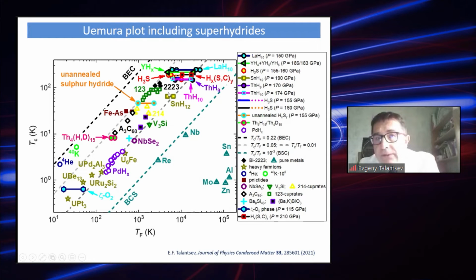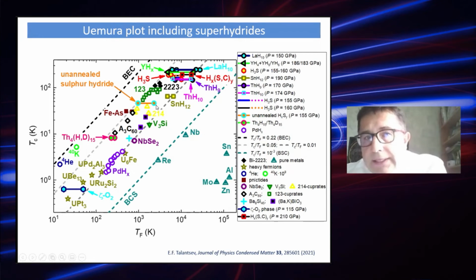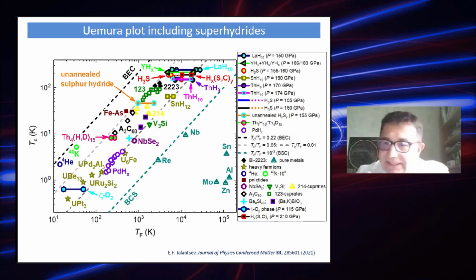where it operates here, and if it has a lower transition temperature, like in tin hydride, it is still within this band. Also, because sulfur hydride can be obtained without annealing, it is placed exactly under the YBCO. And what is important, it was mentioned today by Professor Takano, that oxygen is located just below the heavy fermions, near the heavy fermions.